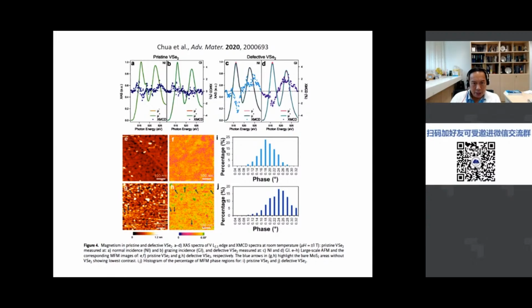And below are MFM images of the surface. E and F are pristine, and G and H are annealed, so it's defective. If you look at them carefully, you can probably see that there's an increase in magnetism in the defective structures. Those bright high contrasts are due to the MFM phase regions being shown. And if you plot out from the spatial data the percentage of this surface in a different phase, because this is a phase image, you see that there's an increase in the percentage of this surface being at a different phase. And that's indicative of surface magnetism of the defective surface.